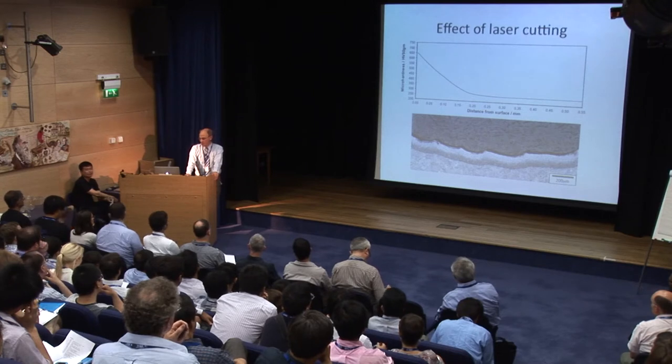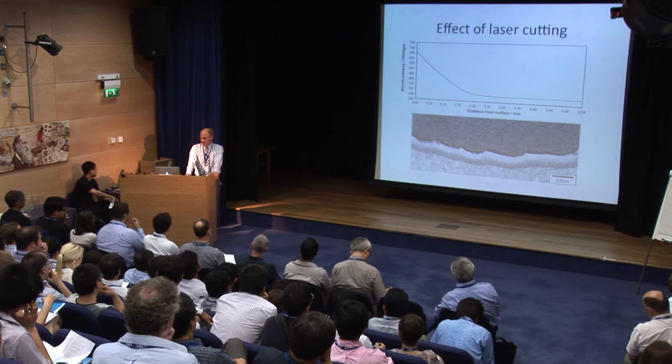because we were hoping and planning that the steel would be able to be formed to a limited extent to curved shapes. And if the steel had been cut by laser cutting, a martensitic edge would make cracking from the edge very likely, and this is what actually happened. And so laser cut steel has to be either dressed or heat treated to remove the martensitic layer before it can be successfully bent.